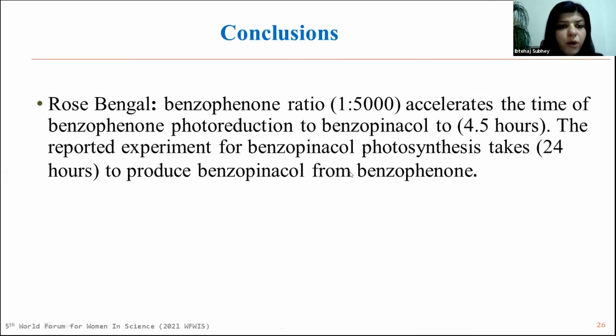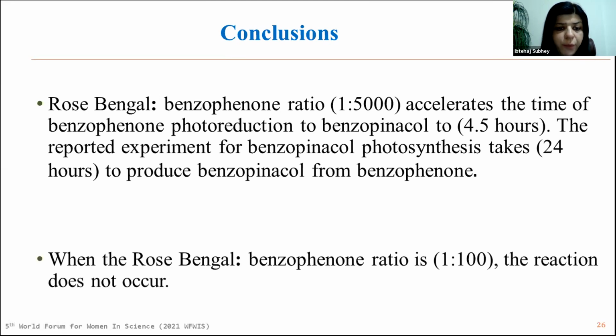Conclusions. A rose bengal to benzophenone ratio of 1 to 5,000 accelerates the time of benzophenone photoreduction to benzopinacol to 4.5 hours. The reported experiments for benzopinacol photosynthesis take 24 hours to produce benzopinacol from benzophenone. When the rose bengal to benzophenone ratio is 1 to 100, the reaction does not occur.